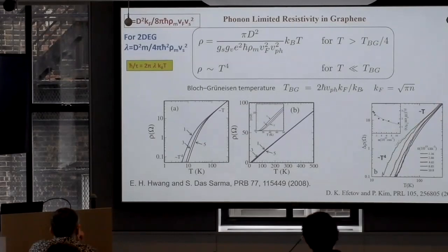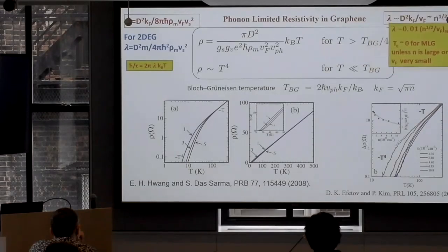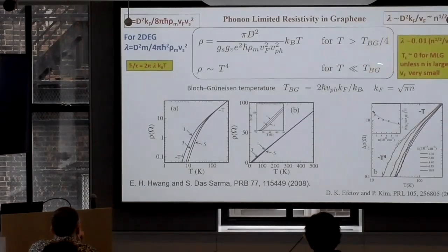And so we get an estimate of the deformation potential coupling, which I think is of the order of 30 electron volts. And when you put in the 30 electron volts, you get a lambda which is very, very small. This lambda is the dimensionless effective electron-phonon coupling that comes into the theory of superconductivity, made famous by the great late McMillan. And this is essentially zero. It's 100 microkelvin or 50 microkelvin, something like that. Now you can't get superconductivity.